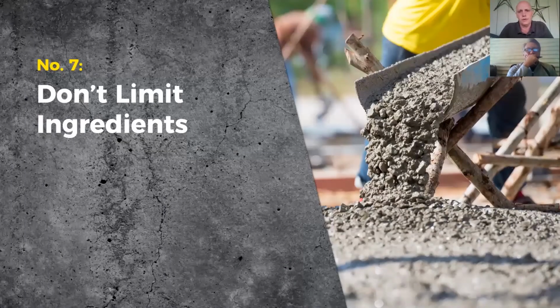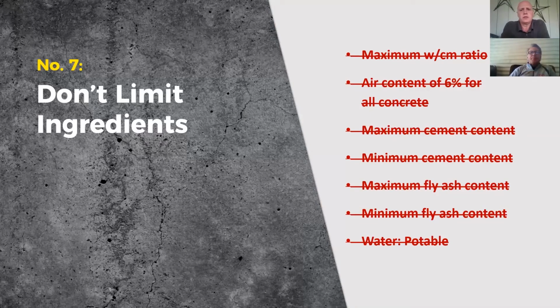Number 7, a little more difficult, although it just requires some diligence from your specifiers, and that is don't limit ingredients. The tendency is to try to limit certain ingredients in concrete, and really that does limit the concrete producer's ability to meet performance criteria, let alone reduce a carbon footprint. Let me explain. Oftentimes we see specifications that have limits on water to cementitious materials ratio. In most cases, requiring a maximum water cementitious materials ratio is unnecessary and drives up cement content. There are times when a maximum water cementitious materials ratio makes sense, mostly for cases of concrete exposed to freezing and thawing, but it's not necessary to actually call it out in the specification. Identifying the exposure class of the concrete per ACI 318 and 301 will suffice. The requirements for water cementitious materials ratio for concrete exposed to freezing and thawing are all outlined in those specifications.